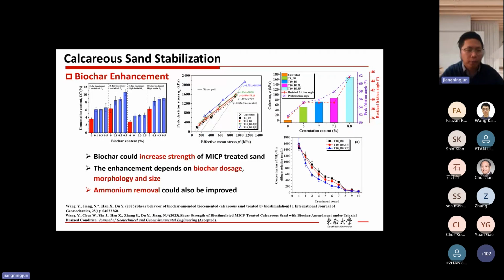So in this particular test, we used two types of biochar. One is needle shaped, so quite long and big. The other is in powder shape, so it's quite fine. Okay, so when we mix the biochar with calcareous sand and do MICP treatment, then we measure the cementation content.